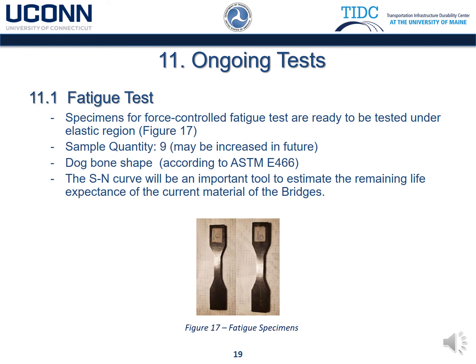Ongoing tests. Fatigue test. Specimens for force control fatigue tests are ready to be tested under the elastic region. The test protocol will be defined by the ASTM E466 standard, and the ultimate goal is to create the S-N curve, which will help us to estimate the remaining life of the material from the selected bridges.